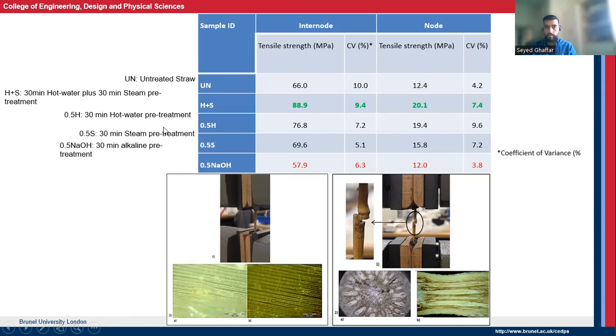And I did the separate effects. I studied the separate effects of hot water washing for half an hour on the tensile strength and the steam. And you can see most of the contribution to the high tensile strength is coming from the hot water treatment of 0.5 hours.